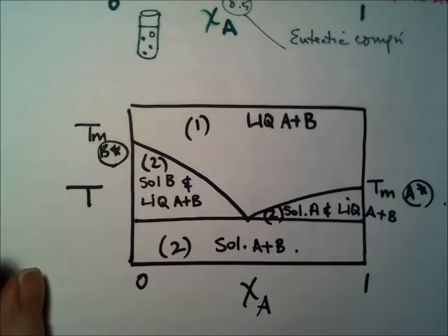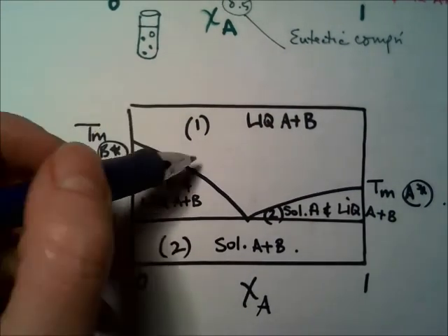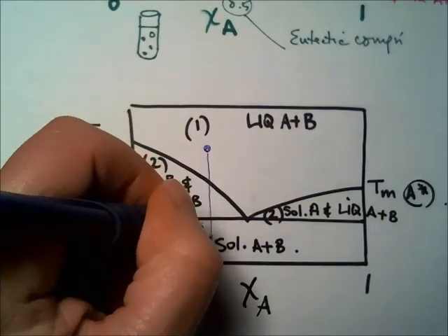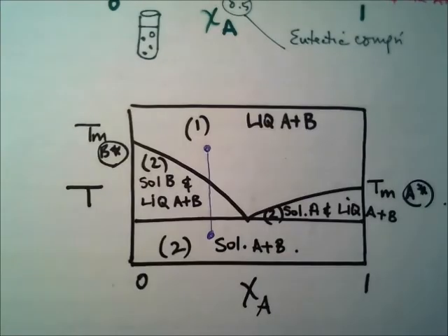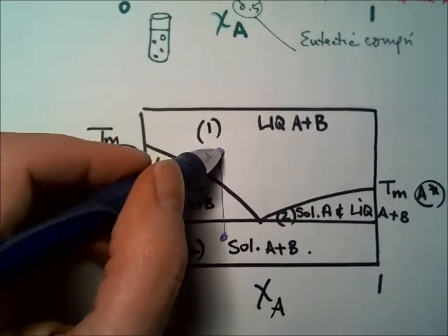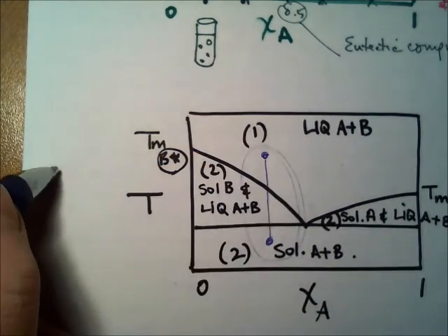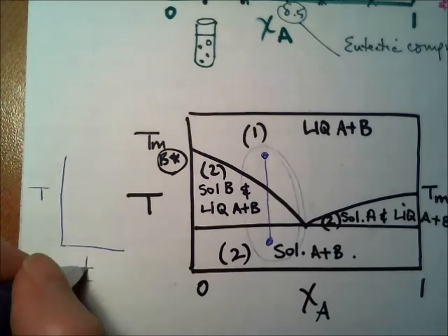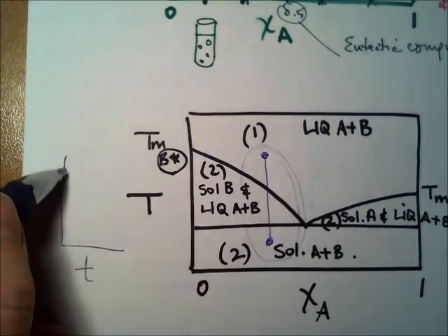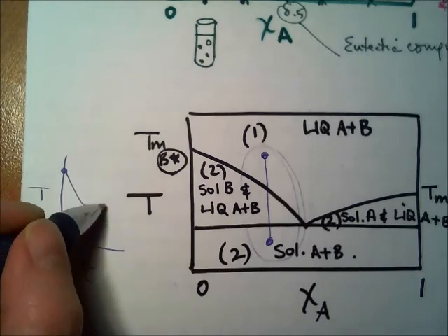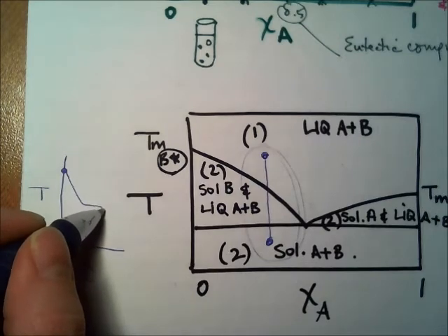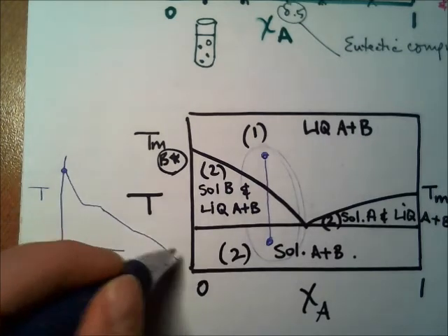Okay, so cooling curve. The cooling curves that you collected can be represented as vertical lines on this diagram, right there. So let's do this. Let me move that over. So that line right there could look like T versus time cooling curve. We start up here, we cool, there's the pure guy coming out, no supercooling this time, getting better at it, maybe a slight different slope, and then again.